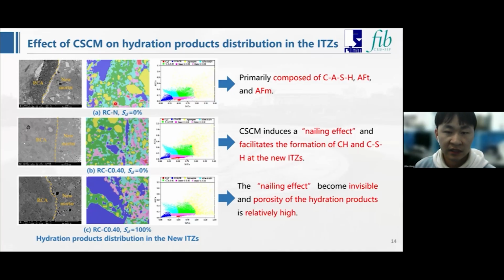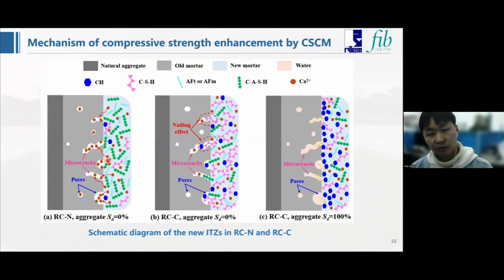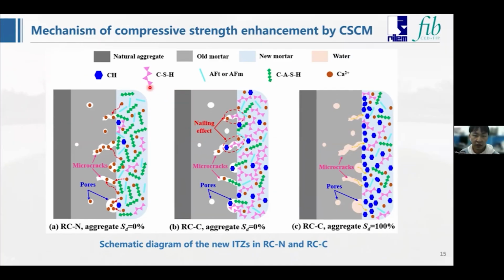However, when the concrete is made by CSCM, the CSCM induces an nailing effect and facilitates the formation of CH and CSH at the new ITZs. When the aggregate SD reaches 100%, the nailing effect becomes invisible, and the porosity of the hydration products is relatively high. Above all, the CSCM induces an nailing effect and facilitates the formation of CH and CSH, which strengthens the bond between new mortar and the aggregate, thereby enhancing the compressive strength of the concrete.